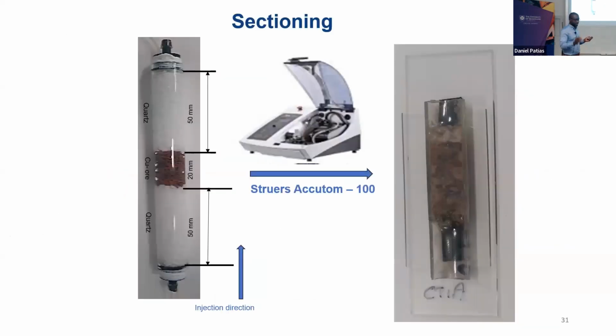So in sectioning, after the experiment, I'll normally flow water through it first to get the excess residues out. And then I put acetone and epoxy in a 1:2 ratio and flow it through as well so that you get epoxy in the material. Then put in a Struers Accutom, which is a really good equipment piece, so you fix it there and then you're able to cut automatically without cutting with a saw and breaking apart the integrity. So you take that, you section, you get this.